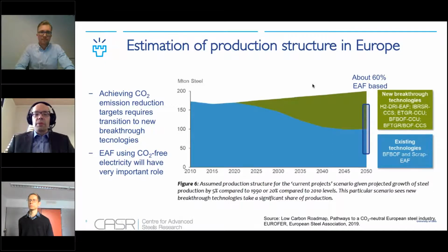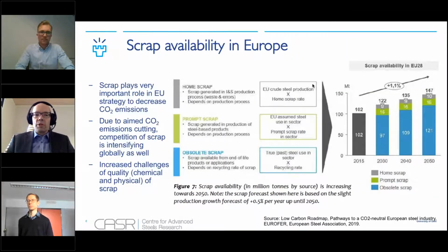And if you look at the scrap availability in Europe, we can see that scrap plays a very important role in the European Commission strategy and the European companies' strategy to decrease CO2 emissions. We can divide the scrap into 3 parts. There is home scrap, which is generated in iron and steel production, and the volume and the quality depend on the production processes. And then we have prompt scrap, which is generated in production of steel-based products, and again it depends on the production processes. And then finally, for the third part, we have obsolete scrap, which is available from the end-of-life products and applications. And this depends on how much we have this kind of scrap. It depends on the recycling rate of the scrap.